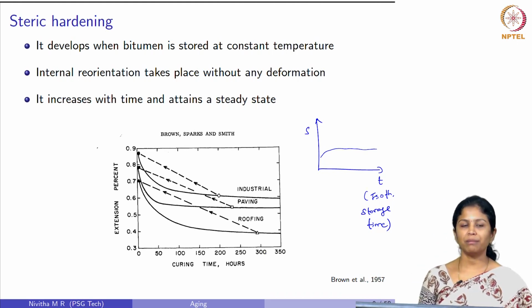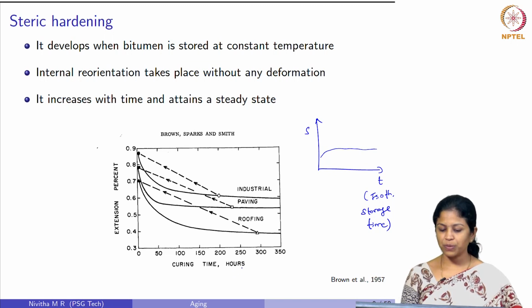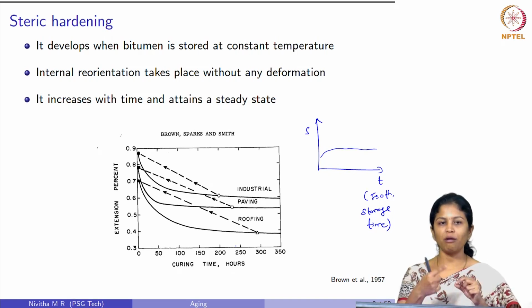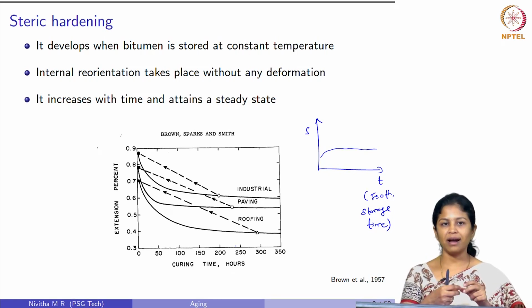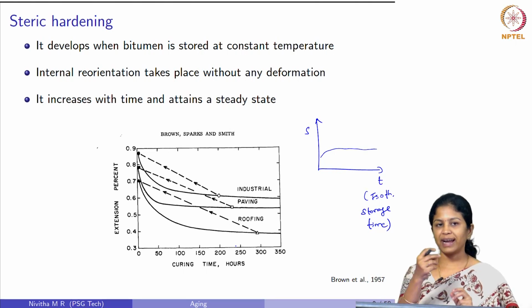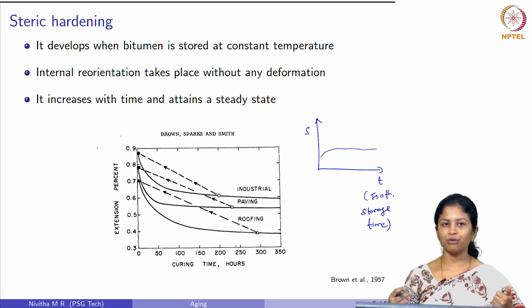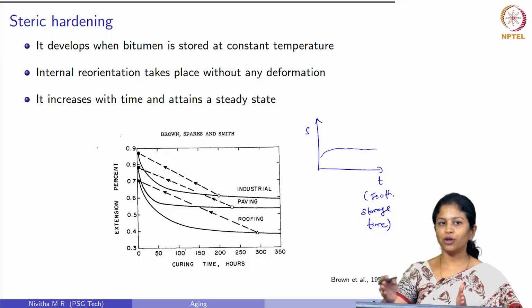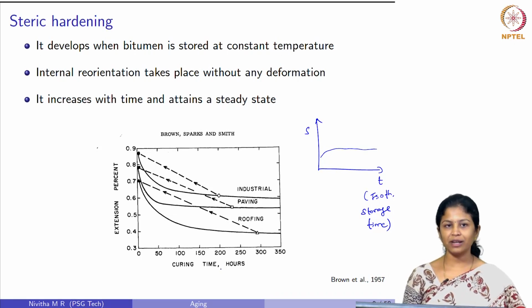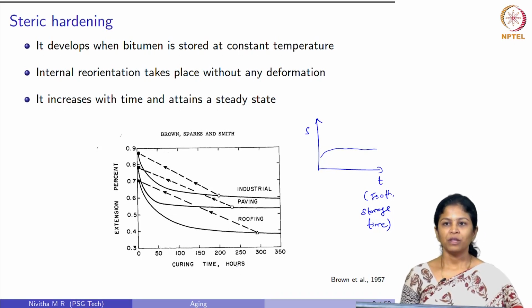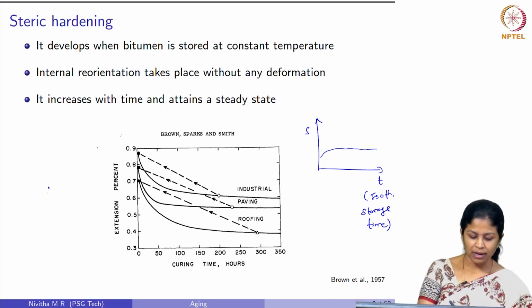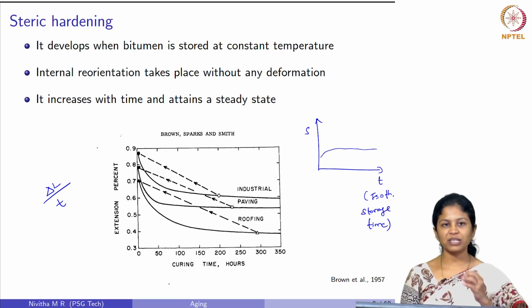This was measured by an interesting experiment which was conducted by Brown, Sparks and Smith. What they had done is that they had taken a bitumen in the form of a cylinder, 25 mm in diameter and 100 mm in length. They had subjected it to an extension test at different curing periods. They had calculated the percentage extension. So, what is this percentage extension? It is the change in length over the original length of the sample.